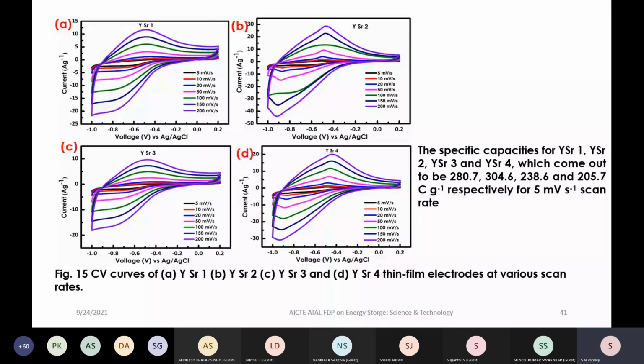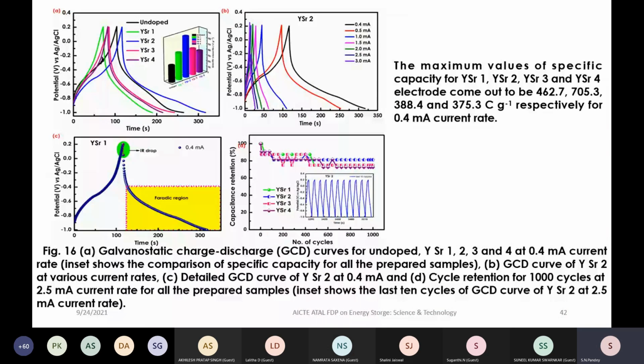So CV, this is a CV curve for the 1 atomic percent, 2 atomic percent, 3 atomic percent, 4 atomic percent, and this is going to increase your specific capacity. So specific capacity is being increased. Then one can go for the galvanostatic charge discharge curve for the undoped, and the 1, 2, 3 atomic percent doped strontium hydroxide. Due to this, what we obtained is that its specific capacity is going to increase, and then one can see the capacity retention. So capacity retention is also going to increase here.